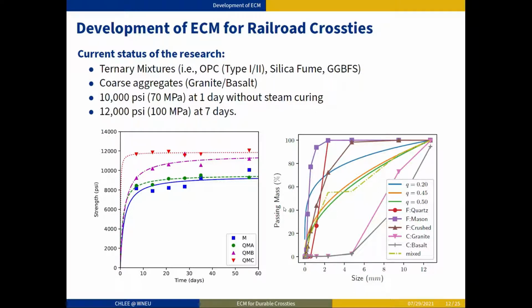So here is our current achievement. Please note that we are still working on this project for making better and durable concrete cross ties. We use ternary mixtures for the cementitious matrix, which includes Type I/II cement, silica fume, and ground granulated blast furnace slag. Also, we carefully chose coarse aggregates, which are a mixture of granite and basalt types. As a result, we achieved 10,000 psi at 1 day even without steam curing. Also, we got 12,000 psi after 7 days, and the strength development curve with respect to time is shown on the left panel of the slide.